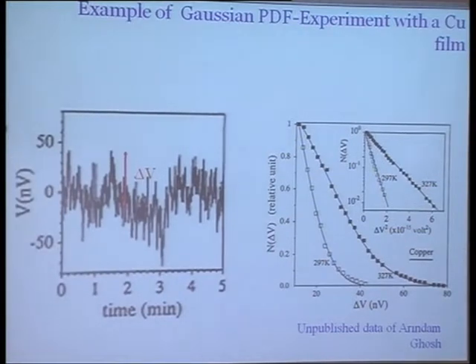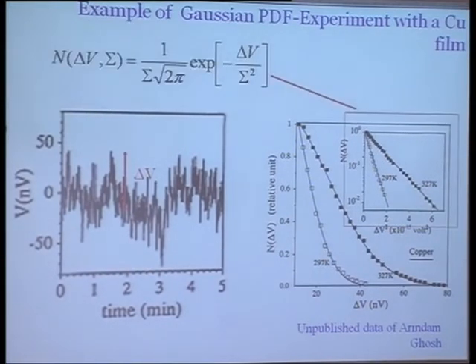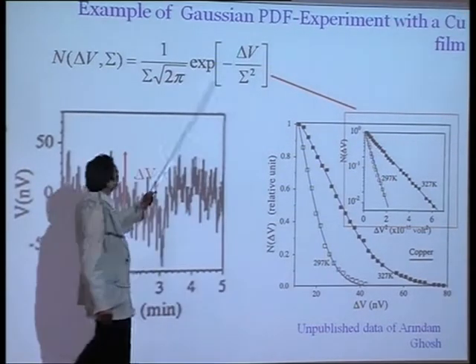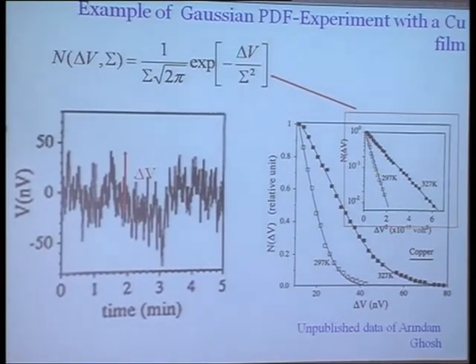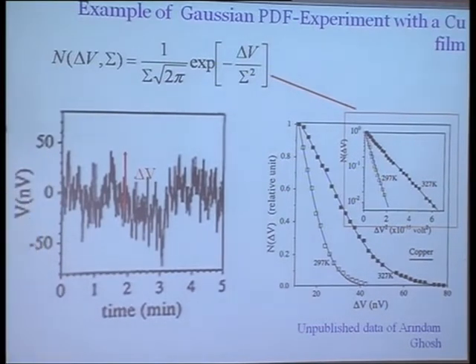And if you don't plot it in a linear scale, but plot it in a log scale over here and the delta V square over here, you can immediately see that this fluctuation follows a Gaussian, and this width is really giving you the RMS fluctuation.